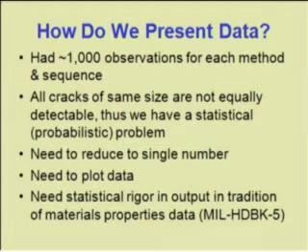And all the cracks of the same size don't respond equally. All cracks are not created equal in terms of NDT response. So the small cracks can give big signals or small signals. So we have a spread. So we've introduced a variance in the detection process. There are many others. But the bottom line was that it had to be reduced to a single number.